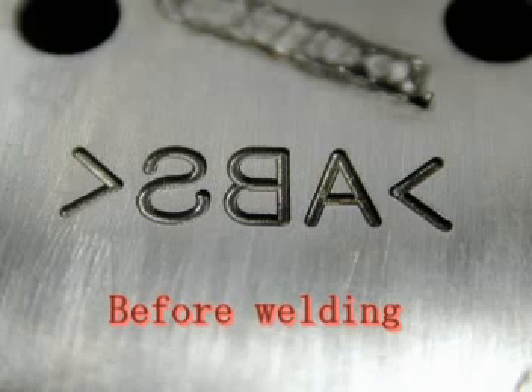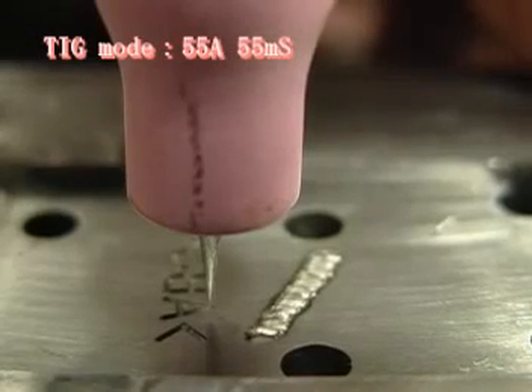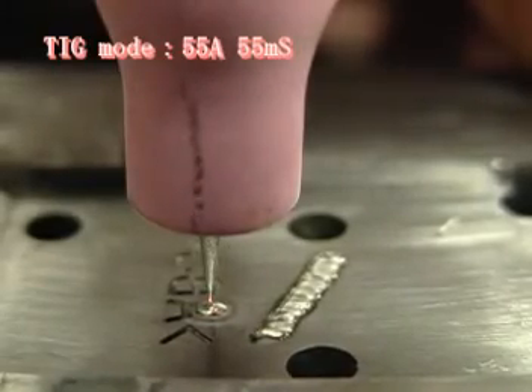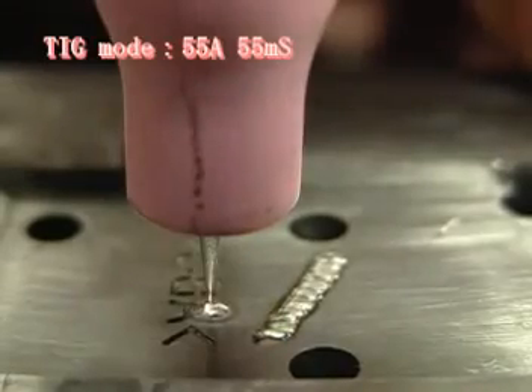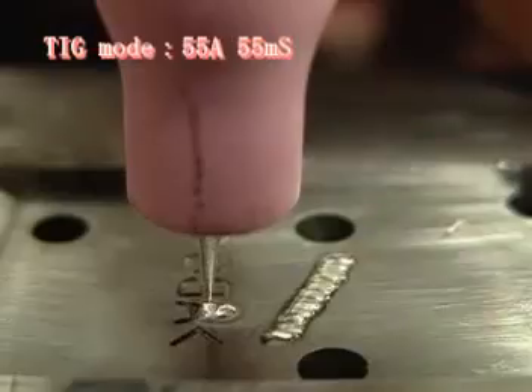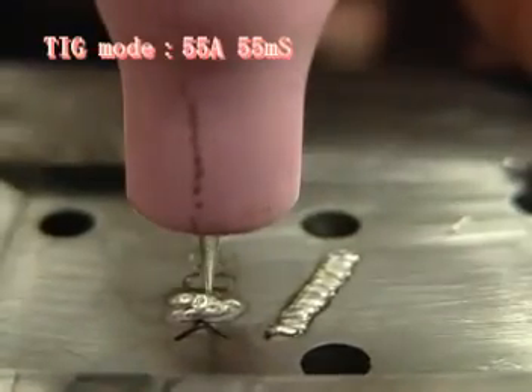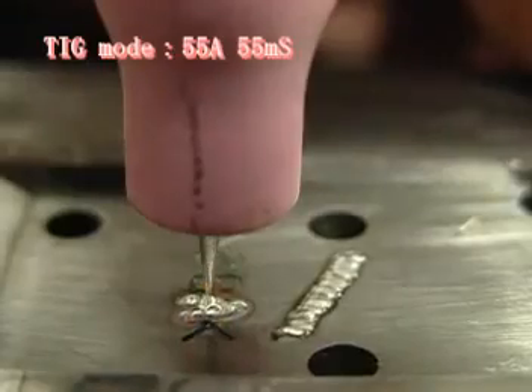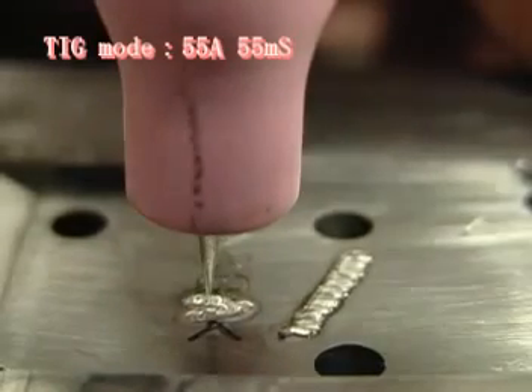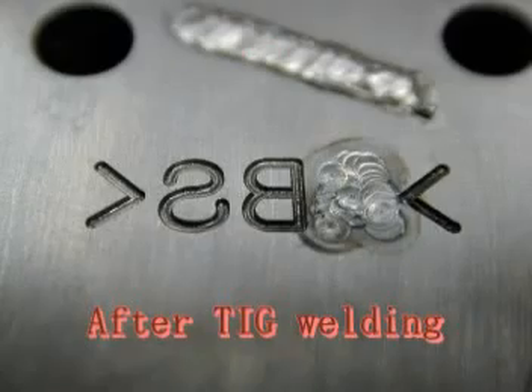Next, I will show you how to erase stamped characters by welding. First, hit the target point using a hammer before placing welding materials. By hitting the stamped characters, the depth of the depression becomes shallow and you can avoid pinholes after welding. The result is like this.